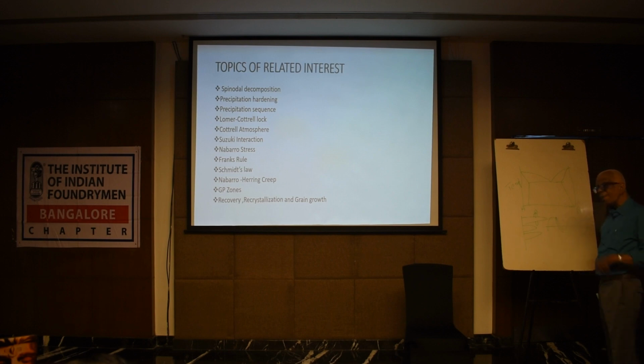So that shows GP zones decompose in the early stages by spinodal decomposition. There is an uphill diffusion. That's the landmark. When you work out the mathematics of spinodal decomposition, you can see the diffusion coefficient is negative. That means there is an uphill diffusion. Normally, diffusion is down the concentration gradient. Normally, it occurs downhill. There is a flux of solute. But in spinodal decomposition, there is an uphill diffusion. It goes uphill. That's the landmark. It's crazy, but I bet that's the truth. You have to believe me. So that uphill diffusion causes decomposition.